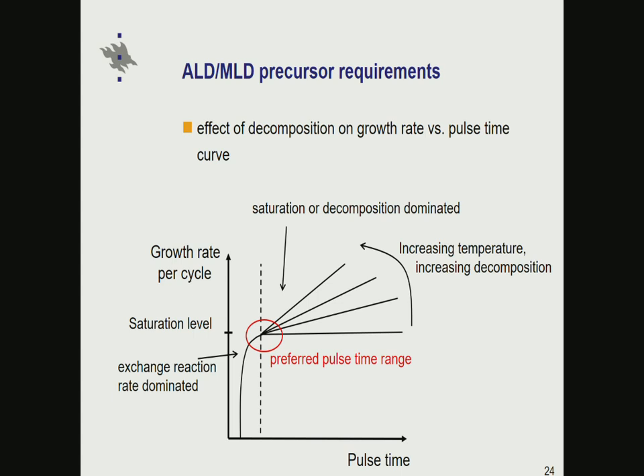But even in this case, where decomposition is there, one can reasonably well divide the growth regimes in two parts as a function of pulse time. In the beginning it is dominated by exchange reactions, so the metal precursor reacting with the surface groups left, for example, by the water pulse in the previous step. And only once these exchange reactions are completed, more or less, the decomposition sets in. And if one wants to run this kind of ALD-CVD combination process still at higher temperatures, this is typically the pulse time range one should be using, so that exchange reactions are completed, but decomposition is still kept to a minimum.